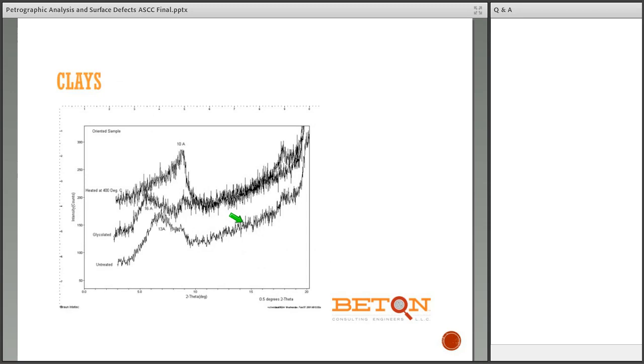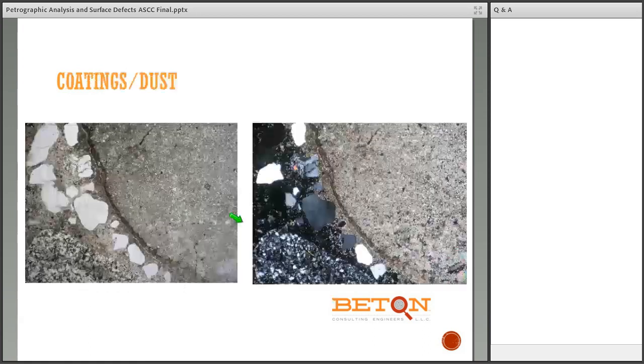And when we're looking at clays, I like to use X-ray diffraction. This is an untreated clay, and then the same clay exposed to ethylene glycol vapors and then heated to 400 degrees centigrade. This pattern with all 3 together indicates to me that it's a bentonite clay, and that's the identification.